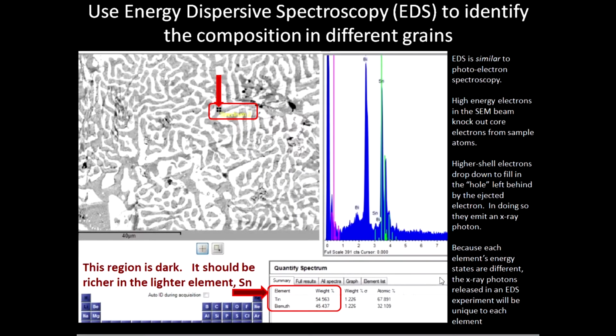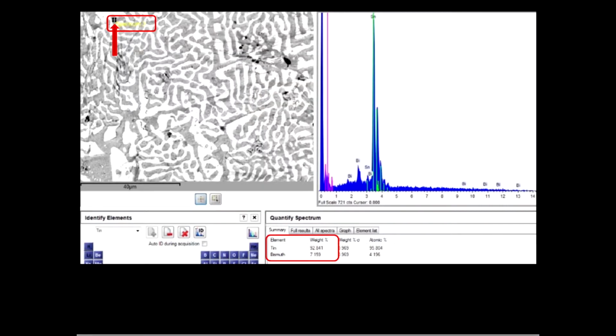So let's take a look and see if we can see similar results in other places on here and verify our results. Here we're looking at a dark area right where that crosshairs is, and you can see the spectrum. It's interesting, compare this to the last one. You can see that this peak in the last slide was really high for bismuth, so there must have been a lot more bismuth in that sample compared to tin. And the tin peak is much higher.